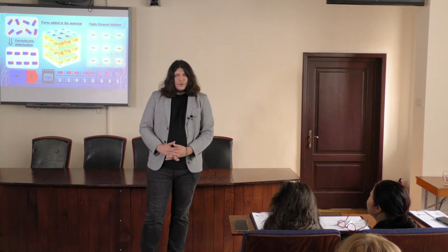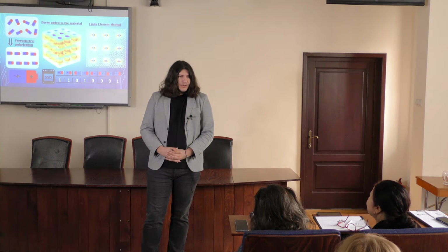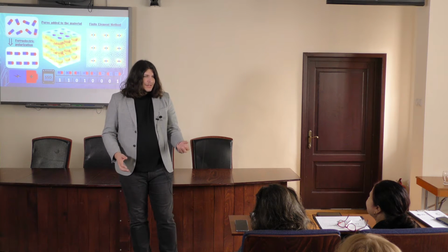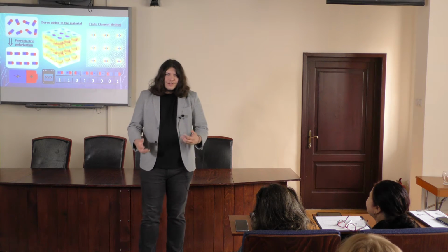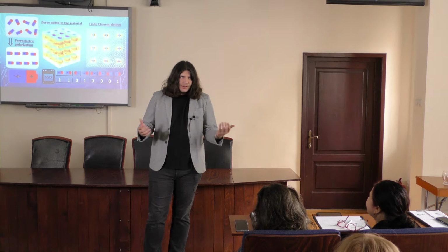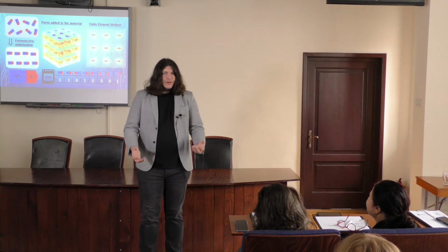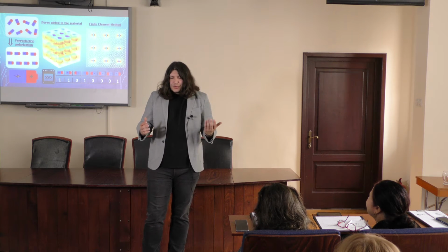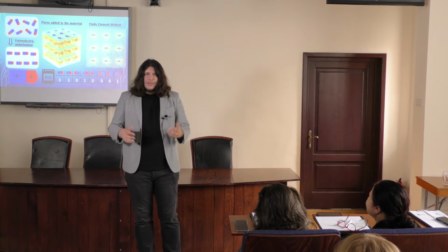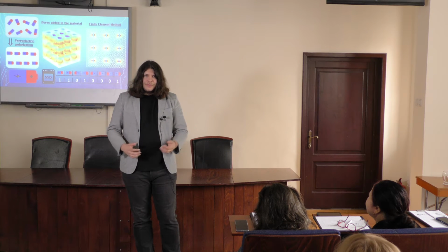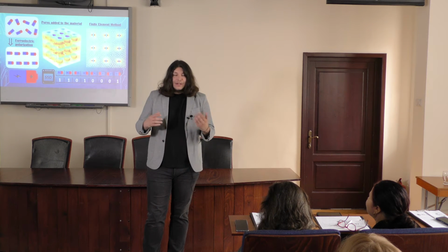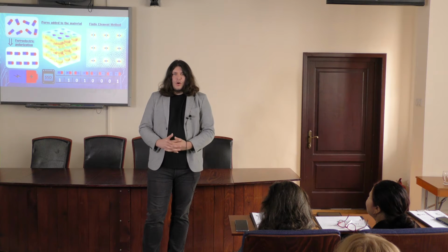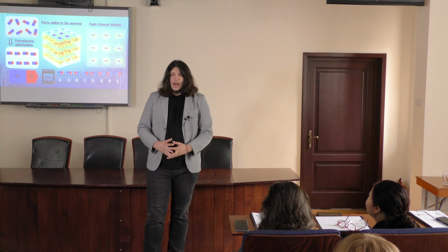My research focuses on porous ferroelectric materials. It may sound a little bit strange, because by inducing porosity, one is removing material from the bulk, and this means removing the little batteries in discussion. But the truth is that those pores concentrate the field, and even though the number of batteries is smaller, they are a little bit more powerful, and the effect can enhance.